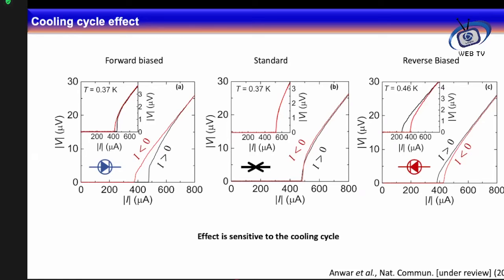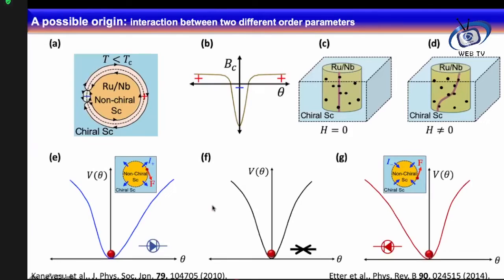Then in this case, if I change the cooling cycle, in the first cooling cycle it can be forward biased, and then in any other cooling cycle it can be standard, or it can be reverse biased. So this selection of forward biasing or reverse biasing is just a random selection of this system.